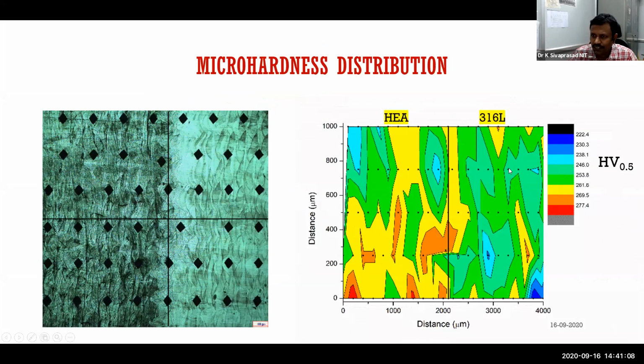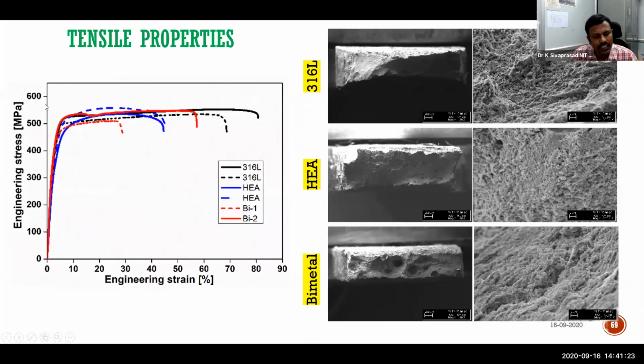Good deviations are there from 316L to HEA, but it's a gradual variation, from a yellow rich region to a gradually green rich region. So there is no abrupt change. That has given us almost the same strength with only ductility variations. Then we have seen the ductility variations also: wherever porosity is there, only in those locations is it being fractured.